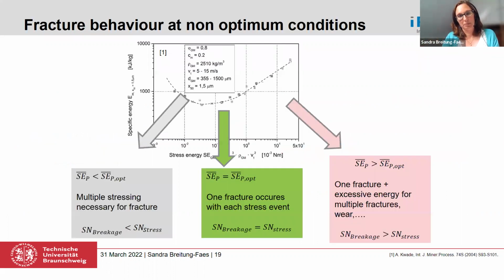Maybe to make it a little bit more clear, I would like to come back to the first figure I showed you. This alpha value reflects the slope of the curve at the right and the left-hand side of the optimum. Because the thought was, if you go to the left-hand side of the optimum, you will need multiple stressing events to make a fracture possible, because the transferred energy is too low to break the particles at even one stress event. And if you go to higher values, well, you will have more fracture pieces by giving more energy to it.